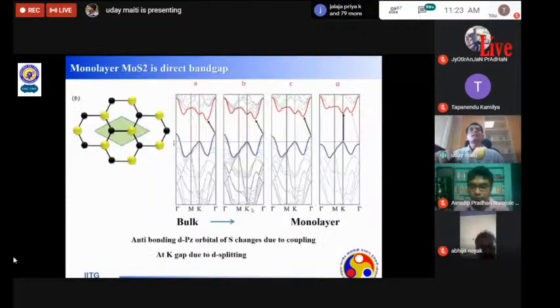And this is the monolayer of MoS2, where you can see that in the bulk phase it is an indirect band gap semiconductor, but when it turns into the monolayer, a single layer, it changes into a direct band gap semiconductor due to the removal of the interlayer coupling.